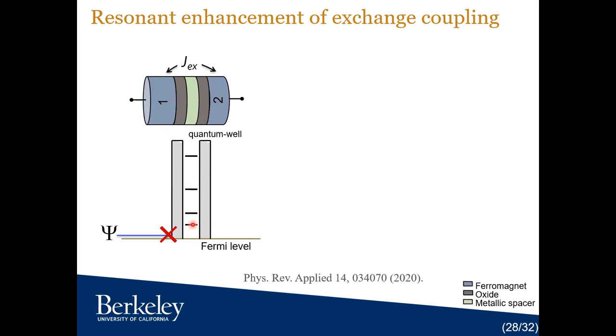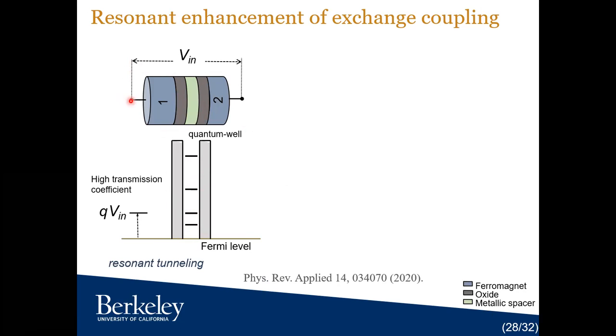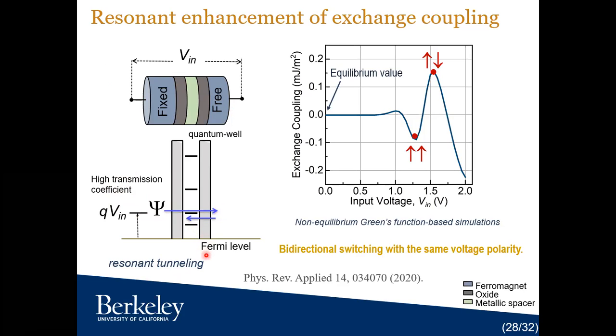This is very interesting because now you can apply a voltage across the structure, and that voltage will change the quasi-Fermi level of your contact. When your quasi-Fermi level is at one of these discrete states, the transmission coefficient between left and right becomes very high. That is very well known as resonant tunneling. So now your wave function from the left magnet can propagate to the right magnet and come back and create that interference pattern. That was our hypothesis, and we did sophisticated NEGF based quantum transport simulations to test our idea, assuming realistic material parameters.